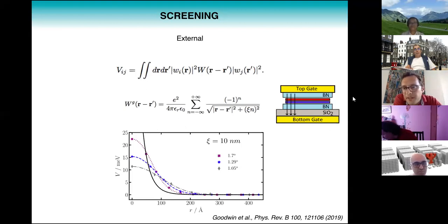So here you see a typical device setup, and the electrons, of course, feel the presence of the boron nitride substrate, which is a dielectric, but then they can also feel the presence of the metallic gates. And so the presence of these metallic gates, through the well-known image charge interaction, can drastically modify the interaction between electrons in the graphene. And this is, of course, something that can be tested experimentally, but something you couldn't do, for example, in the cuprates. You can't play with the electron-electron interaction in the cuprates in that way.